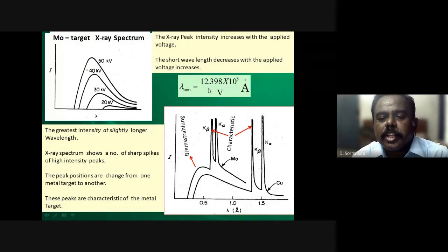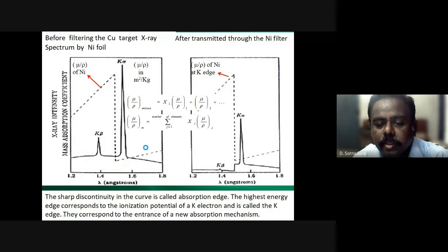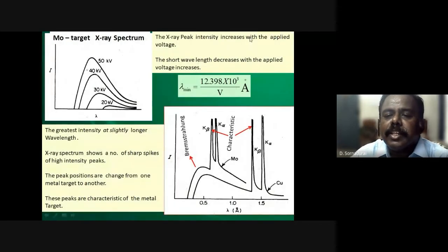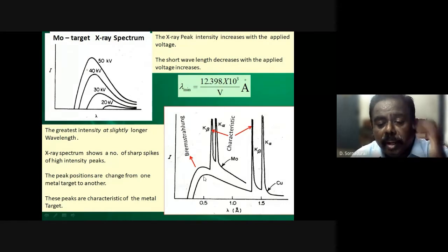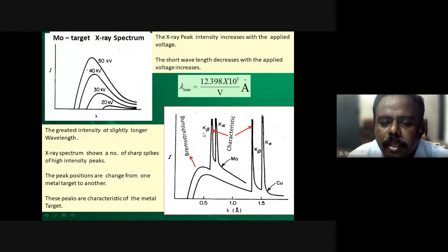That is coming from this formula. So the X-ray peak intensity increases with the applied voltage. Similarly, the short wavelength limit decreases with the applied voltage. Here you can see that I have shown two spectra in this graph. One is the copper spectrum, and this is for the molybdenum. You can see there are characteristic lines like K alpha, K beta for the molybdenum. Similarly, for copper also there is a K alpha, K beta. But mainly we will be using this copper K alpha instead of the molybdenum.